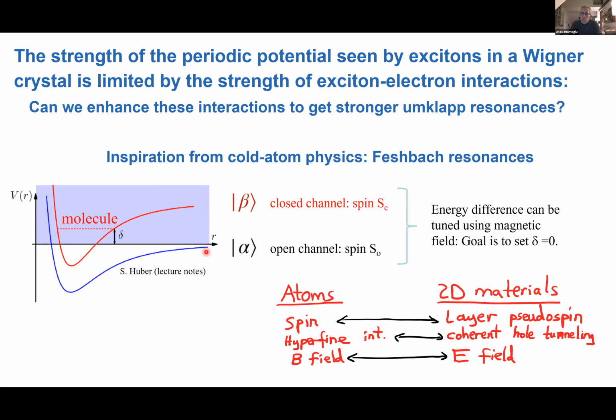I want to show you, even if briefly, that we can do this in two-dimensional materials. We cannot really use spins, but we can use layer pseudospins. Instead of magnetic fields, we'll use electric fields to tune the different channels. The mixing of the open and closed channels with different spin in atoms is typically due to hyperfine interaction, and in our case, this will be coherent also.